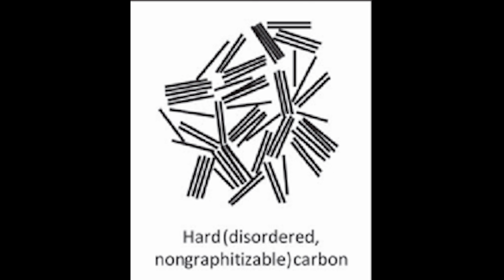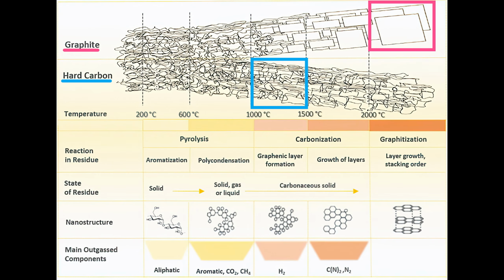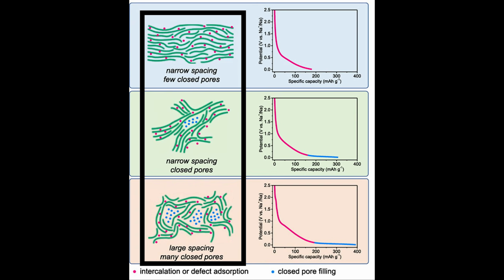It's because hard carbon plays better with sodium-ion electrolytes, and it's cheaper and easier to manufacture than graphite because the disordered structure requires less energy and refinement. As for ionic resistance, it's highly variable depending on the structure of the specific type of hard carbon. But there are hard carbons available that offer low ionic resistance for fast charging.